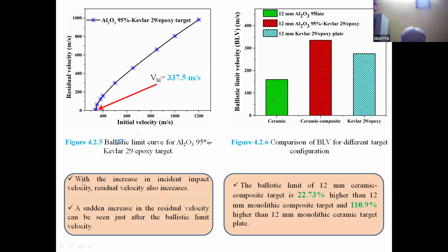And what are the inferences? With the increase in incident impact velocity, residual velocity also increases. That is evident. A sudden increase in residual velocity can be seen just after the ballistic limit velocity. So this is another observation.